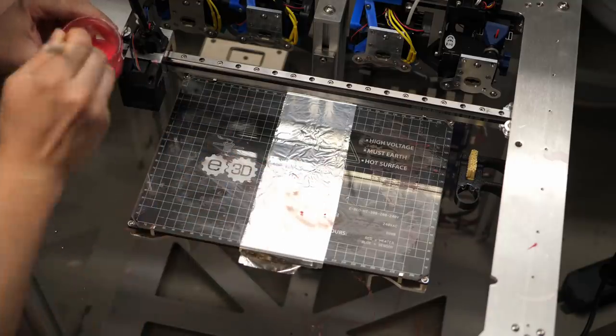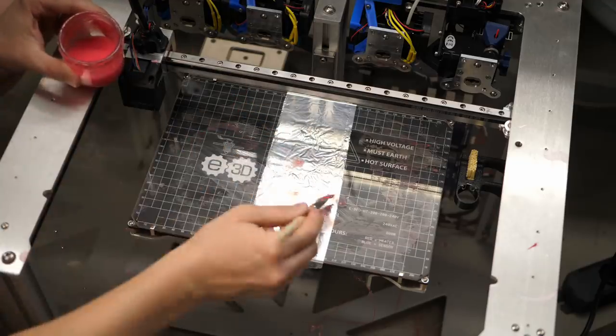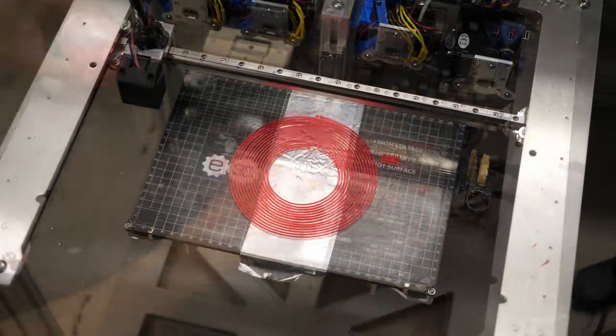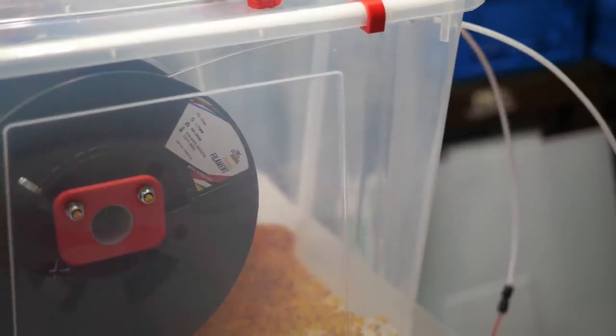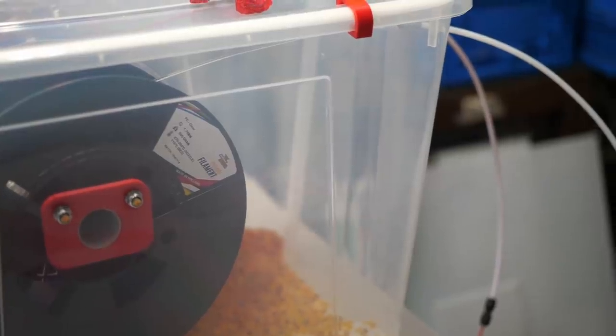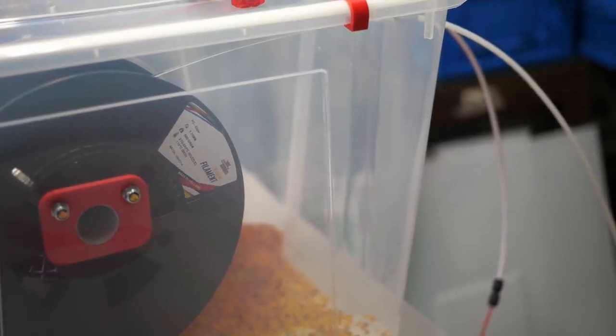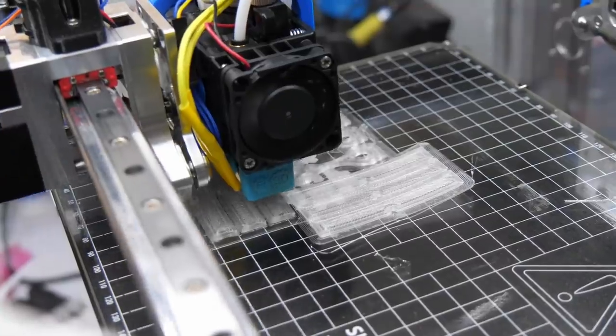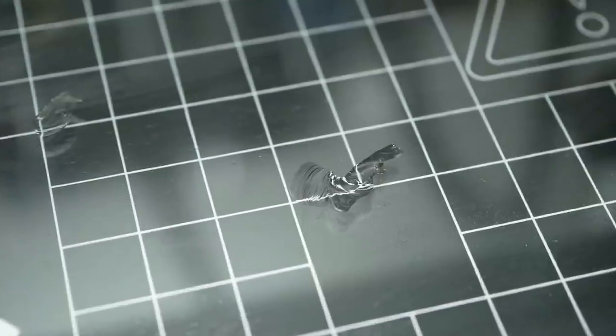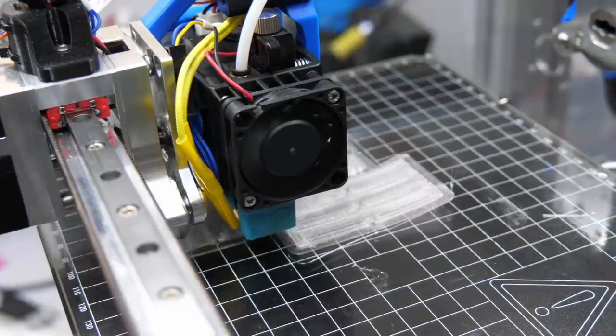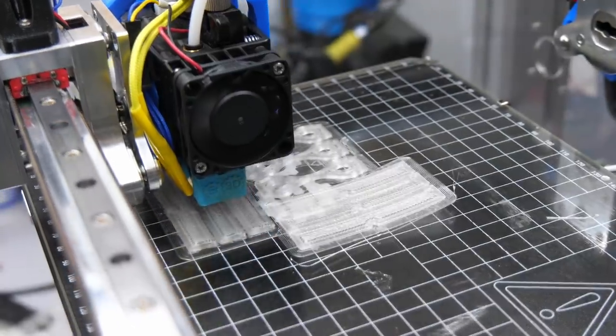The second problem was mesh bed leveling with my tool changer. That was a bit buggy in the version of RepRap firmware that I used at that time. It's fixed now, but I upgraded the firmware only recently. Therefore, first layers were not always perfect and sometimes sections lifted. The base materials that I used for the dual material filaments were Spoolworks ABS that I printed at 245 degrees Celsius and Hobby King's Premium PC printed at 280 degrees Celsius. The PC itself was a bit of a pain to print on the glass bed because it either didn't stick properly or it ripped pieces of glass out of the surface. In the past, I had more success printing it on the smooth PEI of my Prusa with either glue stick or Magigoo PC.